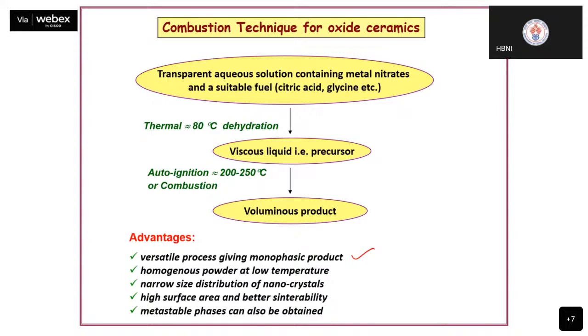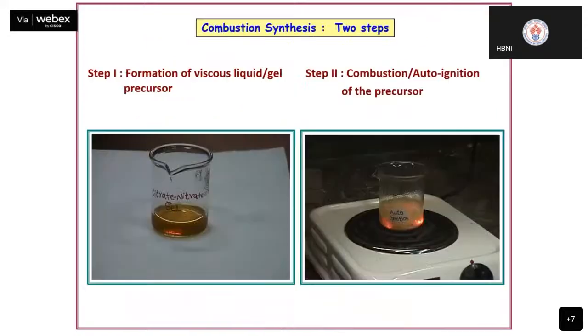Like I don't want to go to 1500 to get my product. But if I do a gel combustion earlier, even if I don't get the product, I'll get a powder which has the mixing of the reactants in nano form and in homogenized form, so that once I heat them, I will need very low temperature to get the same product as compared to if I had started with bulk or micron size powder reactants. I get homogeneous product powder at low temperature, narrow size distribution, high surface area, and because the reaction is happening in a fraction of a second, metastable phases, kinetically stable phases can be obtained.